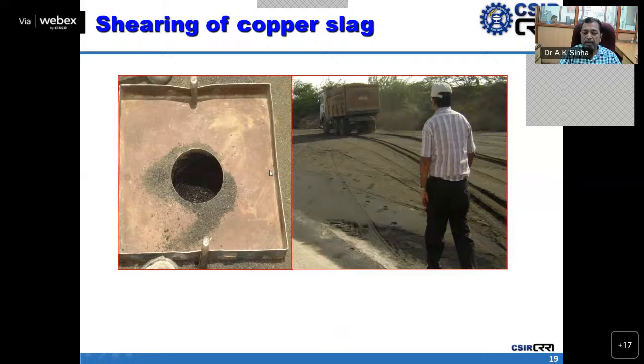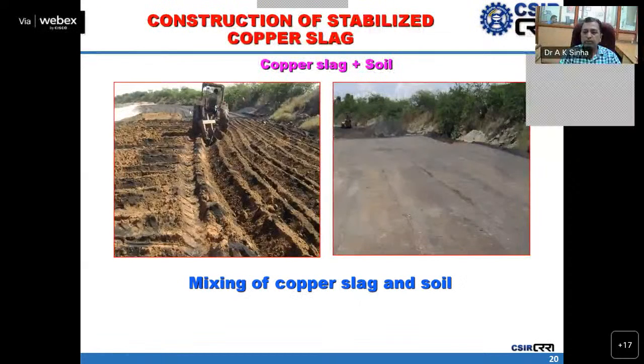But what happened when a loaded truck plied on this for the second layer, we will see under the wheel, the copper slag was segregated under the wheel. So it means we have examined that technically it is possible, the parameters pertaining to subgrade and embankment material, but practically it is not feasible. So to increase the cohesion between particles, it was decided that it would be blended with soil or pond ash materials to increase the cohesion properties.